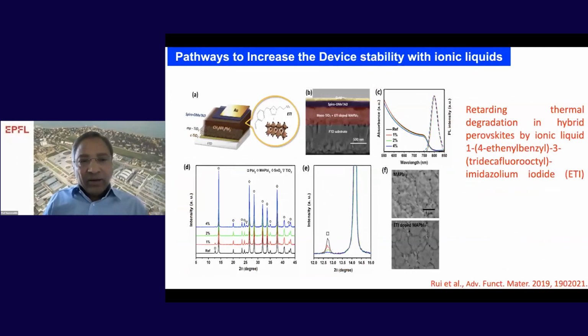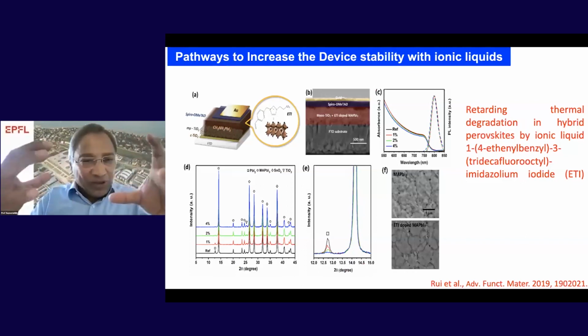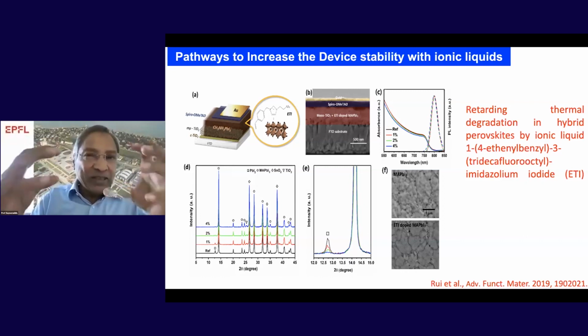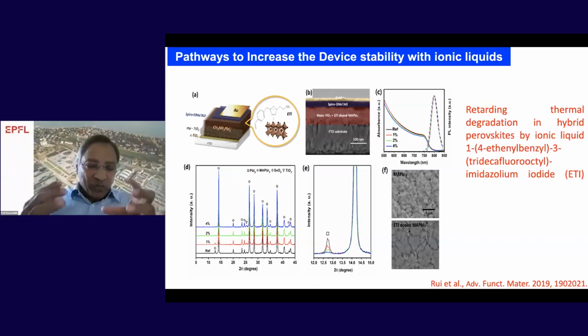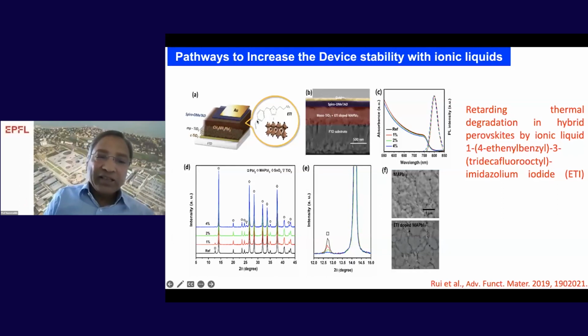Now, I have taken another representative example of how to increase the stability of the perovskite composition. As we're discussing, perovskites are very interesting materials, but ion migration is one of the biggest problems, and ion migration creates defects. How can we prevent this ion migration? So what we have done is we have incorporated an ionic liquid, which has a lot of ions. This is point number one. When incorporating the ionic liquid, we functionalized it. If you look at the ionic liquid here, it has a double bond, which can be a polymerizable group. And then we have substituted the hydrophobic unit here with fluorine substitutions. So the name of the ionic liquid is given here.